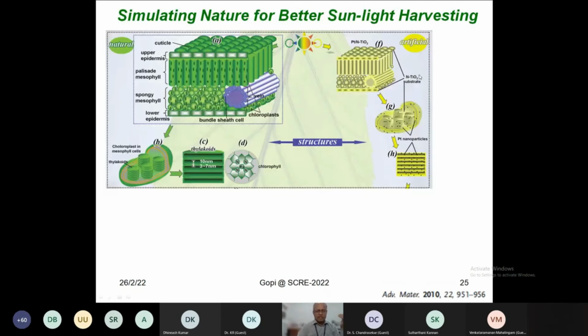Not only that, when we did the same reaction in laboratory conditions, we hardly saw a small amount of hydrogen. We could not see any bubbles like this. So that clearly indicates that sunlight definitely has a role. So it is best to do the reaction in sunlight. That's the first message I want to give.